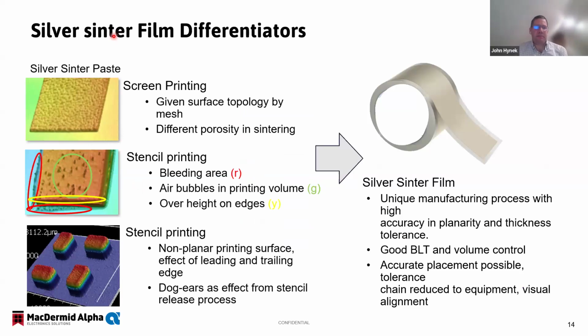When you're printing silver sinter paste, there are multiple different ways you can do it. You can do a screen print, but one of the drawbacks to the screen print is that the surface topology is given by the mesh, and there can be different porosities when you're using screen printing. You can stencil print, which I showed earlier. The drawbacks to the stencil print are threefold. What you can get is a bleeding area.